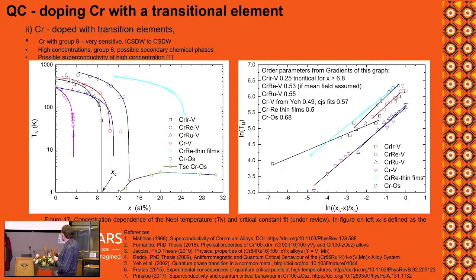The other important thing about group 8s, and there's quite a lot of literature about this, they themselves have superconducting phase transitions, the flow of current without resistance. And we thought, let's see what happens in some of these chrome alloys, because there's contradictory publications on this. And what we found is superconductivity in one of our own alloys, one of our own PhD projects that's sitting here. But the important bit is this.